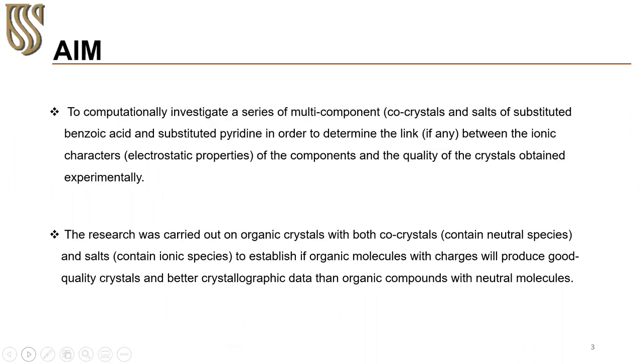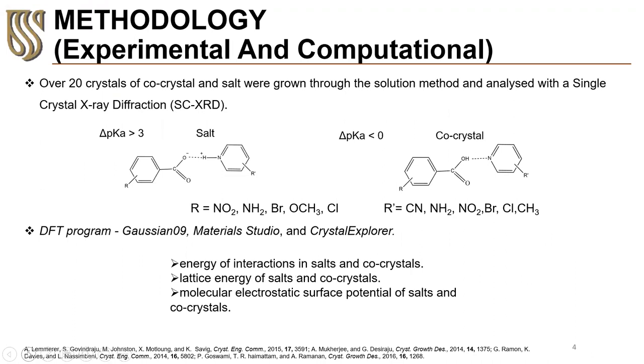We investigated a series of co-crystalline salts in order to assess the link between the ionic character of the component and the quality of crystal obtained experimentally. We synthesized substituted benzoic acid and pyridine in ratio 1:1 using solvent evaporation method. The crystals obtained were analyzed with single crystal X-ray diffraction.